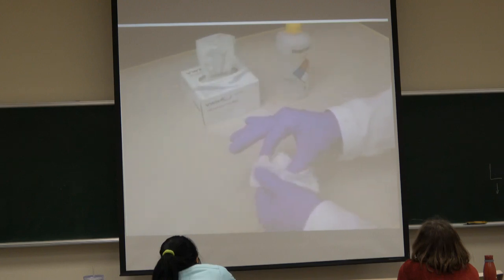Use ethanol on a tissue to wipe off any fingerprints or oils on the slide. Step 5. Put a drop or 2 of the titanium dioxide solution on a slide and quickly spread the solution as evenly as possible over the slide using a clean glass stirring rod. Step 6. Wait for the slide to dry for a few minutes before carefully removing the tape.